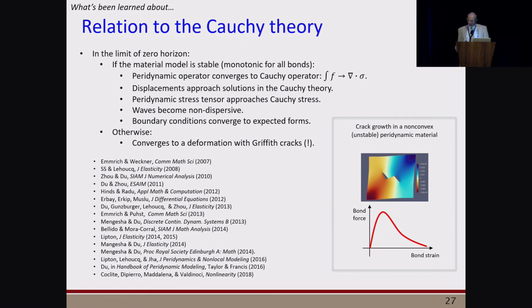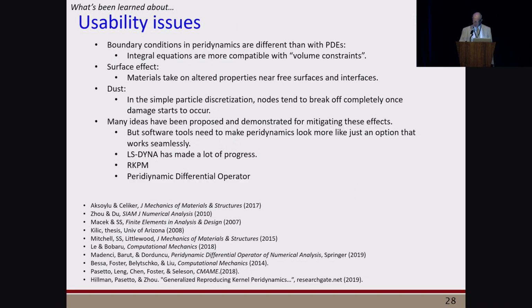Interestingly, if you have a non-convex elastic peridynamic material, meaning the bond forces go up and then down, the limiting case as you reduce the horizon to zero is you get Griffith cracks. In other words, jump discontinuities in the deformation that consume a definite amount of energy per unit surface area as they grow. And then you get the PDEs away from this jump discontinuity. So that's a very interesting result that Professor Lipton at LSU and his team have explored.